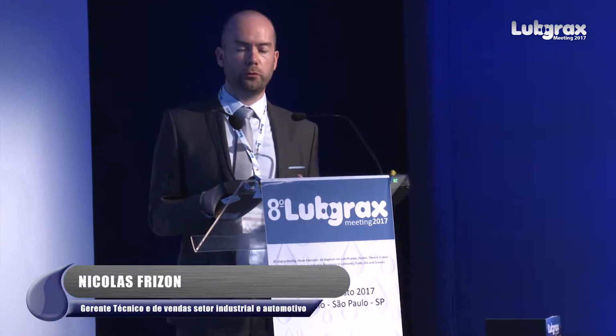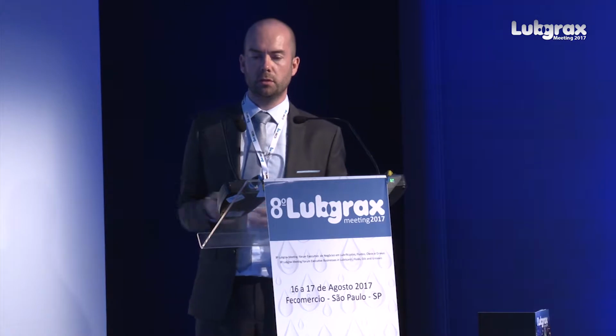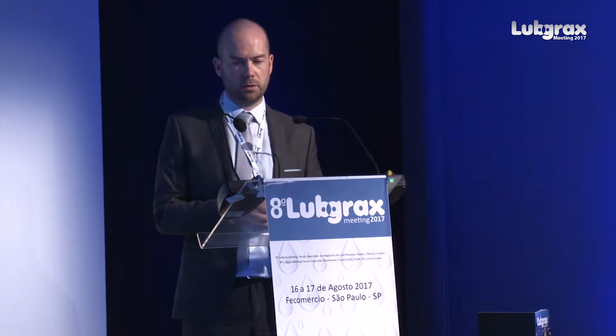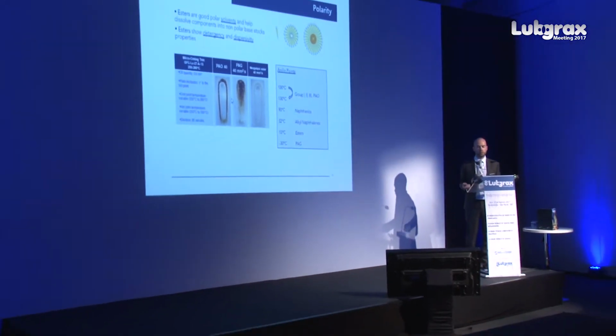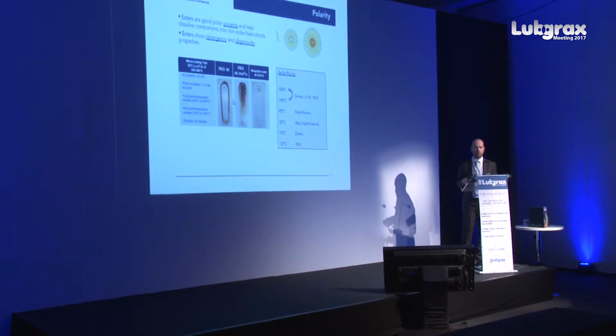In terms of detergency and dispersivity, esters are also very good, and we made micro-coking tests. Micro-coking is a test developed by the GFC. GFC is a French group of industrial part of the lubrication, so NYCO is part of this group. There are also French car manufacturers. This test was developed in order to show the cleanliness you can have with esters, as well as the detergency it brings. It's a metal surface, and you can check the quantity of residue you can have, and by choosing a neopolyol ester, you will have a very clean surface, thanks to the polarity of esters.